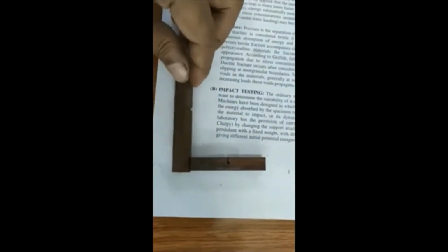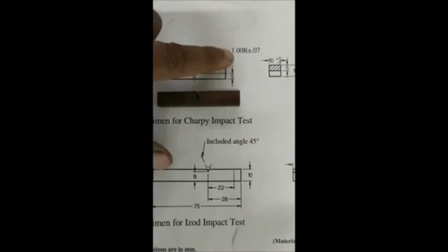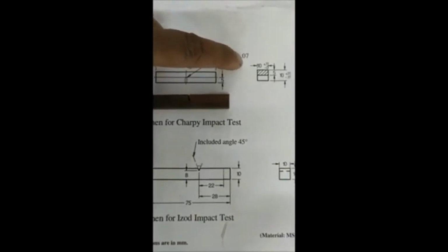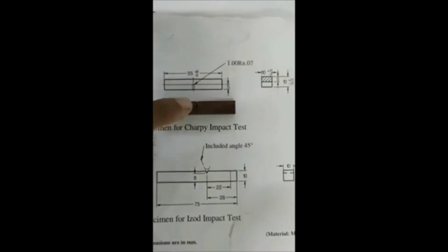This is the Izod specimen notch, and for the Charpy specimen, this is the notch. The notch can be either a U notch or a V notch. So the notch geometry, where to put the notch, and the specimen geometry are all here. For Charpy, the specimen length is 55 plus or minus 0.6 mm, and the notch geometry is a 1 mm root radius plus or minus 0.07. The notch should be made in a milling cutting machine. The width and thickness of the specimen are 10 mm, so 10 by 10, length 55, and the notch geometry is this one.